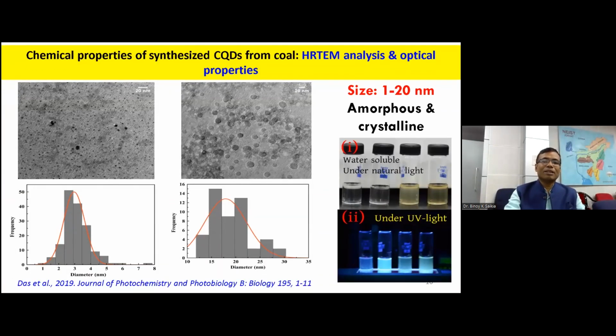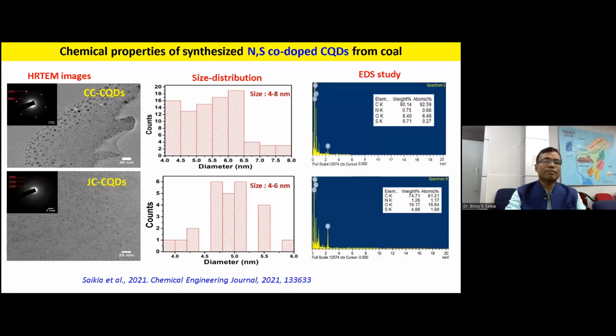So this is the electron microscopic analysis, we got sizes in between 10 nanometer size, and also you can see we are also getting some higher sizes, so the graphene quantum dot can also be present. And it has a very interesting emission color, blue emission in the UV light, and this could also be excitation dependent because it changes with the intensity of the excitation sources, and this is also very interesting.